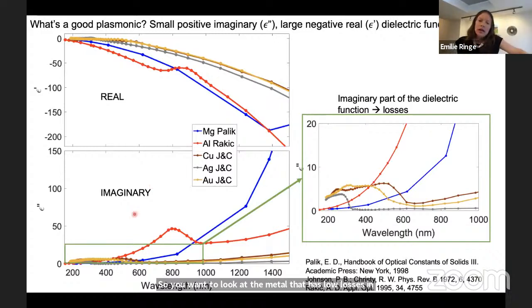We all know that gold and copper have interband transitions, so they're not very good for plasmons in the blue and the UV. We all know that silver is really pretty good. But looking at magnesium, it's pretty encouraging to see that the losses are really pretty low across the UV, the visible, and the near IR.